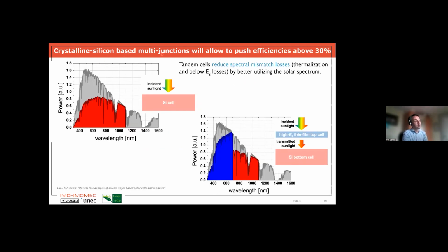A crystalline silicon-based tandem or a multi-junction will allow to push the efficiencies above 30%. So what is the idea behind it? We're going to use a silicon solar cell and we are going to place another cell on top of that. And this top cell needs to have a higher band gap. Then the light will first enter the top cell, and the high energy photons, let's say the blue light, will be absorbed in this top cell. The light with lower energy will go through the top cell and will be absorbed in the silicon bottom cell. So everything absorbed in the silicon bottom cell here in red is more or less the same as what we have here.